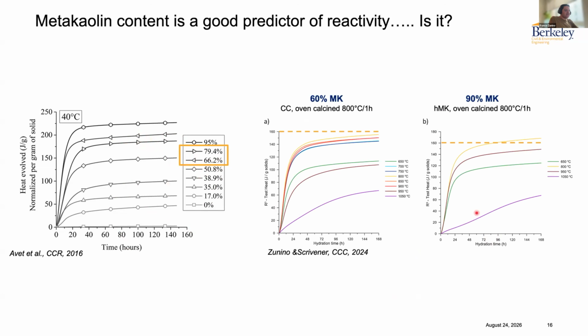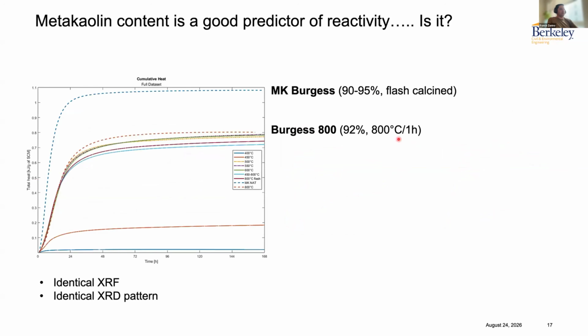And things that we have seen in more recent studies, when we have materials that have 30% more metakaolin than the other one, calcined under the same optimal conditions. However, when we see the total heat evolved in the C1897 test, these numbers do not necessarily correlate with that metakaolin content. Going a little bit more in depth, here we have two materials with essentially identical chemical composition and mineralogical composition that are both pure metakaolins.